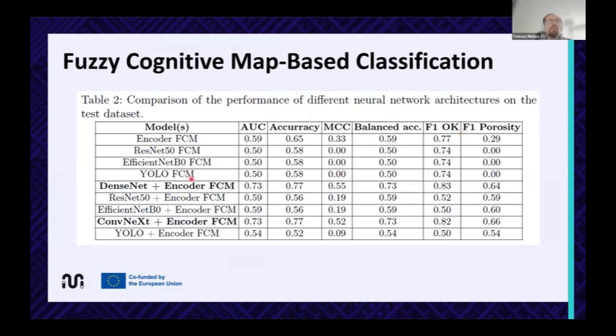And here we have results for the different types of fuzzy cognitive map with extracted features. So we also measured different models, and as expected from the previous step, the best was using DenseNet plus encoder as feature extractor, and then everything was trained using these features in the fuzzy cognitive map. And for this, we got 0.55 MCC and AUC 0.73. So quite high values, but still there is a lot to do and a lot to improve, because yes, this can be still much higher.